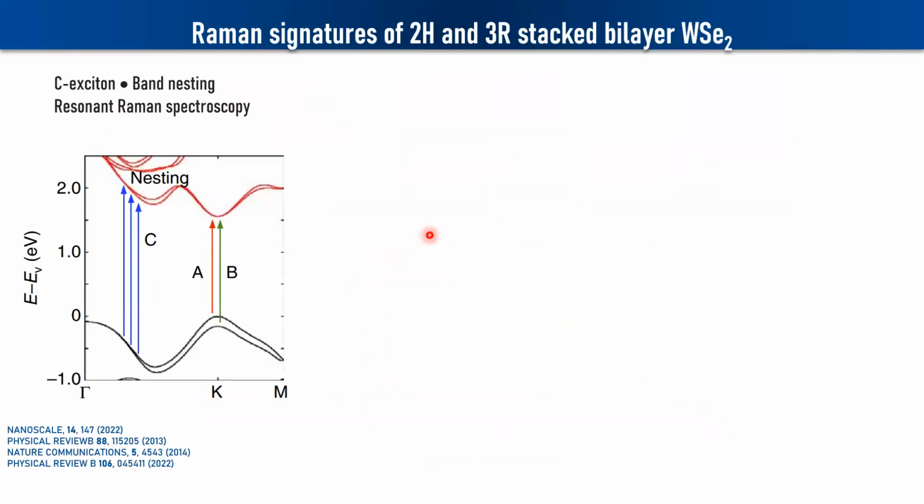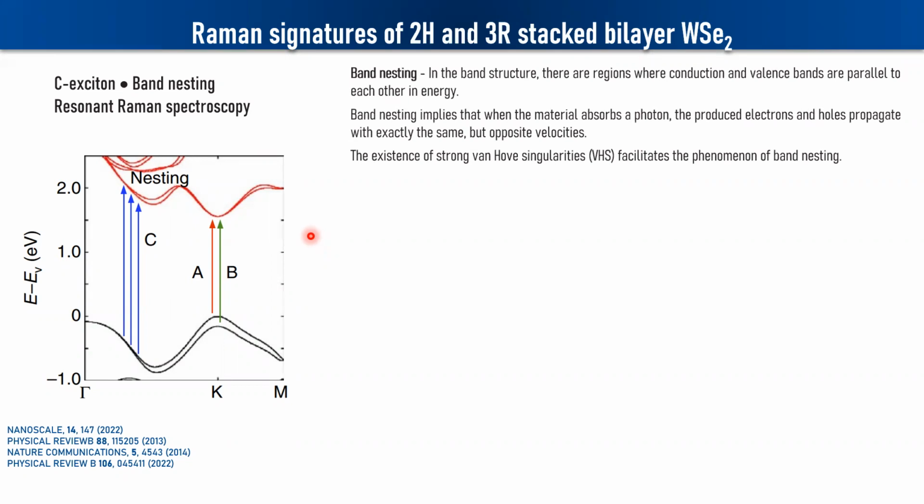The explanation for this is that you can attribute it to the Resonant-Raman features. So what is Resonant-Raman spectroscopy? If the excitation energy is matching with any of these electronic excitations, then you will see a large transfer of energy to the phonons, and you see that in the Raman shift.